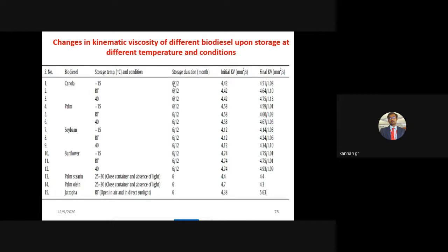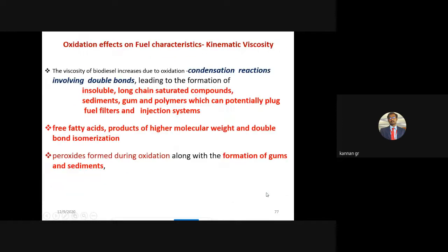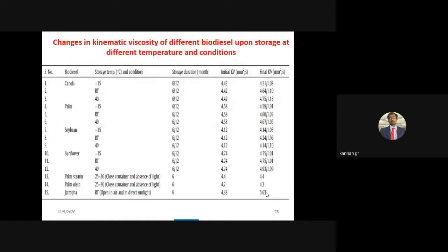Here, yes, one more tabulation which represents changes in kinematic viscosity of different biodiesel upon storage at different temperatures and conditions. Here you can see the first column as usual is the biodiesel, the second column the storage temperature, and the storage duration in terms of months. The viscosity may increase over a period of 6 to 12 months. We see this in Jatropha for storage during 6 months. The initial kinematic viscosity of 4.38 is increased to 5.63 because of these parameters. Some gum and polymer formation can potentially affect the filters and injection systems.